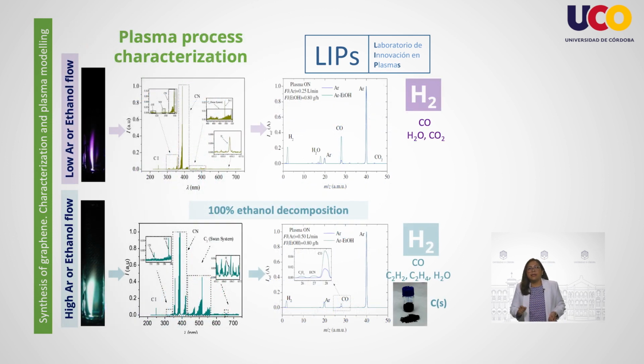With this slide, let's understand the effect of ethanol flow rate on the plasma kinetics by the optical emission spectroscopy technique. As can be seen, the concentration of nitrogen and oxygen from the surrounding atmosphere affects the formation of plasma species at either low or high ethanol flows. Carbon-nitrogen formation is favored over carbon-2, whereas increasing both parameters results in the emission of carbon-2 species, which are related to the graphene formation itself. In both cases, ethanol is completely decomposed and hydrogen is formed as a byproduct.